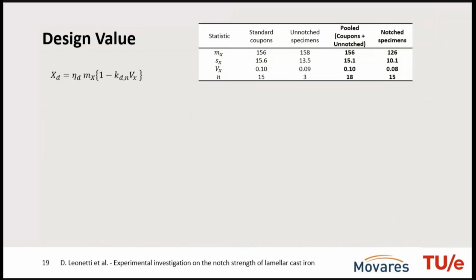You can see here a factor eta. Eta is essentially a conversion factor to account for different utilization. It's a bit controversial, but you might think of it as if you are testing slightly different conditions than the structure will actually experience in service. So if you're testing what you think is a similar condition, then you can keep this value at 1. Otherwise, you should apply a penalty or an allowance for a larger value, in case you are testing, for example, a worst case scenario kind of thing.